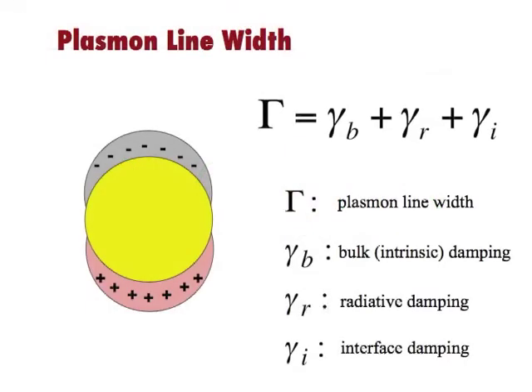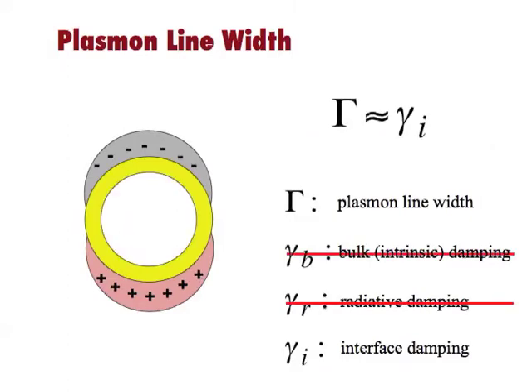The LSPR line width reports on plasmon coherence, but its analysis is complicated because it is affected by numerous processes in addition to interfacial scattering. These include bulk or intrinsic damping and radiative damping. For many particle systems, the line width is dominated by bulk damping. We have shown that by changing nanoparticle morphology, in this case to a hollow structure, the sensitivity of the LSPR to changes at the interface can be increased.